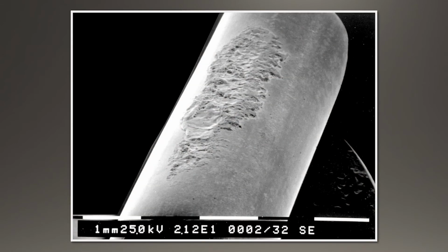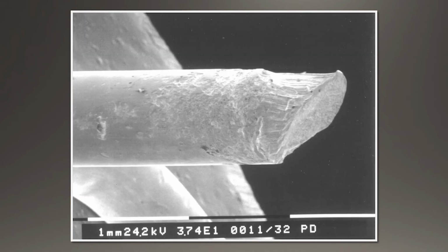So here we go. This is a copy of the wire that's got a very poor surface. And this is usually caused by fines that are present in a wire during the wire drawing process. Here's a wire break. And again, there are some surface defects near the break. This was probably caused by fines inside the drawing die, so that there was very poor lubrication, leading to a high force on the wire, and a resulting wire break took place.